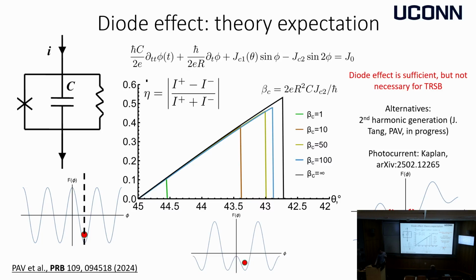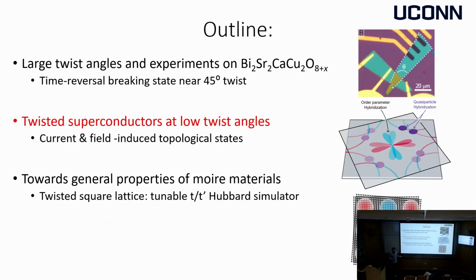Okay, so far I talked to you about the physics of the order parameter, and I didn't even mention electronic physics, the physics of quasiparticles, and no magic angles, nothing like that. Some people call 45 degrees the magic angle, but I will show now that there is actually a magic angle similar to graphene in the system. So far, we find that the presence of the order parameters actually endows these twisted systems with new emergent physics at large twist angles, let's say 45 degrees, where twisted graphene would actually be boring because the Dirac cones would decouple. Now I will go into the territory more close to twisted bilayer graphene, and I will try to understand what happens with those Dirac points as I twist.